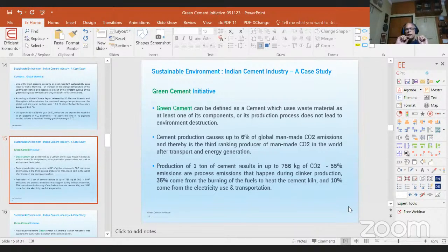Now, production of 1 ton of cement results in up to, as I mentioned, 756 to 760 kgs, that's 0.76 tons of CO2. Almost 55% of it is coming from the process, and that is an inevitability of the cement manufacturing process, because as you know, limestone primarily consists of calcium carbonate, CaCO3, and when you are calcining it, you are allowing the CO2 to be released. So CaO remains and CO2 is released. So almost 55% of emission, on which at the moment we do not have very significant control, is coming from the process emissions.